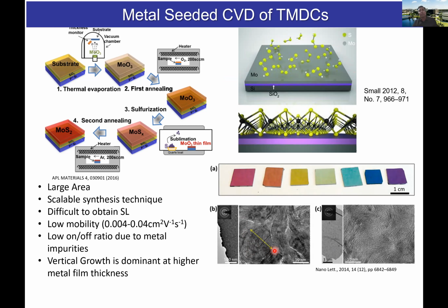In electron transport, grain boundaries are notorious scattering centers, so the mobility will be extremely low compared to single crystal devices. But there are niche applications. People don't mind low mobility samples for certain applications, so for a specific application, it's not bad.